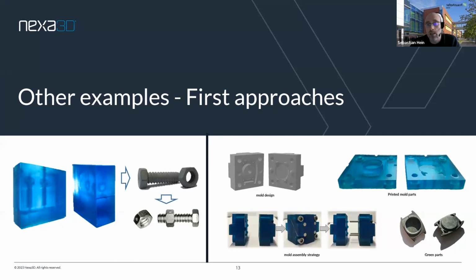We tried some watch cases where we saw some of the issues with removing this material by dissolution, because one aspect that you have to take into account, which I will go into a little more detail on the next slide, is that this material, when you dissolve it, it swells slightly. And now this feedstock that you have, this metal powder filled polymer, is quite rigid, so it's prone to breaking quite easily.